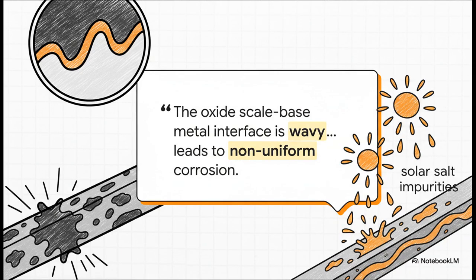The researchers looked a lot closer, and things started to get strange. This quote from the study tells the story. The boundary between the new armor and the original steel, it wasn't a nice, clean line. It was wavy. And that's a huge red flag that the attack isn't happening evenly. Something's going wrong just beneath the surface.